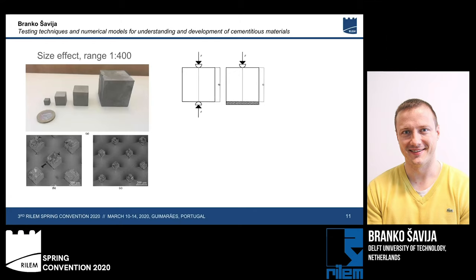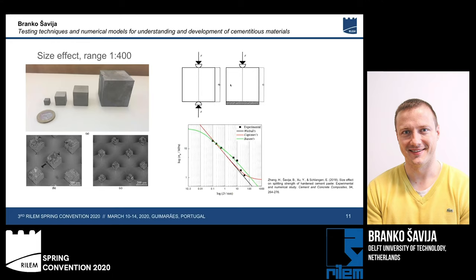Then we can compare our results to different analytical and empirical size effect relations. And here we see a comparison between our results given in black and three most widely used size effect relations. And actually, in the range that we are testing, all three seem to fit quite well. So we still were not able to go to the low range of the size effect curves.